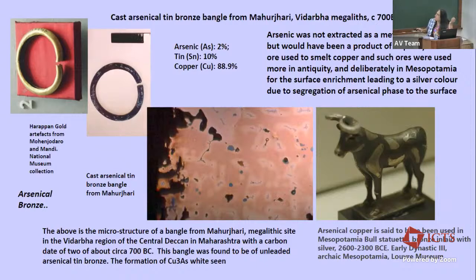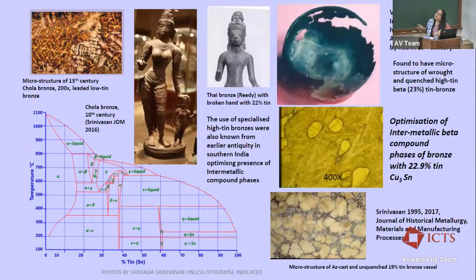I don't know how much you'll understand about metallography, but basically how you get this kind of structure is you cut out a very, very tiny sample if they allow you. But I was very lucky. This is no more than a millimeter or 2 millimeters with a jeweler saw, and you polish it, which is actually very difficult to do. It's much easier to polish large chunks, but very difficult actually to polish archaeological samples and get meaning out of them. And so here you see this particular phase which causes this enrichment, which is the copper arsenic phase here, these little whitish regions around here. And these kinds of bronzes, of course, you don't see them much later. That whole use of arsenical copper seems to die out after that period.